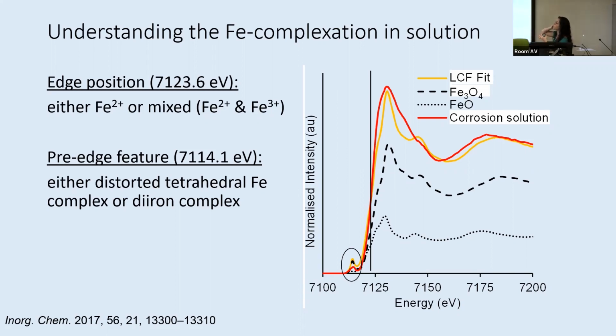So I've circled here the pre-edge feature, which you can see, and then I've also noted our edge position. What's really useful for us to see is that we have probably mostly iron 2+ in solution, and additionally, we have an idea that its preferred structure is either a distorted tetrahedral iron complex or a diiron complex. And while right now this is particularly scientifically detailed information about what's happening in that solution, it lets us start to think about what is the nature of those complexations that we're having and how we can address that situation, either if we don't want it to happen or what types of molecules we might want to screen out because they encourage the degradation or decomposition of the solution. So it's sort of an information is power type of approach here.